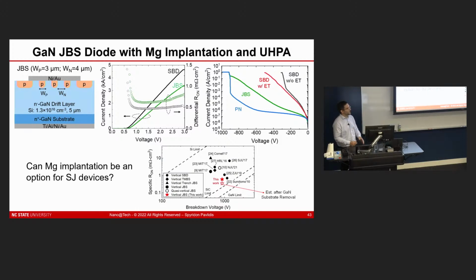So what we've seen, and there are groups out of Japan that have been working very actively in this area as well, is that we mainly see diffusion vertically, and the lateral areas outside of where we did the implantation actually do not allow the magnesium to penetrate that efficiently. So it seems to be driven by damage initially, and that allows quick movement of the magnesium. And then once you repair that crystal, the magnesium diffusion slows down as well. So it's mainly accounting for vertical movement or diffusion of the magnesium there. But that's definitely been something we've been thinking about.